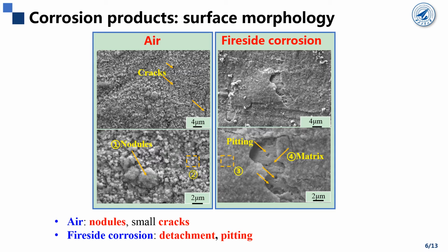First, we look at the condition in air environment. We can see that the oxide scale formed in air is continuous and compact with some nodules and some very small cracks. On the contrary, in the fireside corrosion case, we can find the scale is detached from the substrate and there are many cracks, and also we can see corrosion pits formed in the bare matrix surface.